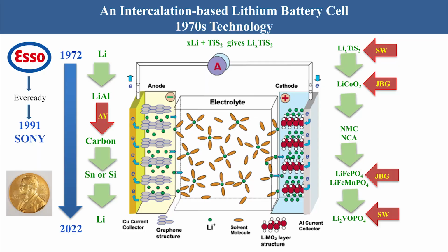The big breakthrough was really when Akira Yoshino in Japan started working on graphite, and the same intercalation reactions as with titanium disulfide. Lithium goes into the lattice, in a very reversible manner. The only problem is you store 6 or 7 grams of lithium for every 70 grams of carbon. So very inefficient, and the carbon takes up half the volume of the cell. So right now that has to go, and there's a lot of work now on tin, and a number of spin-offs from Stanford I know are working on silicon. But our long-term goal is to get back to pure lithium metal if we can make it operate in a safe manner.